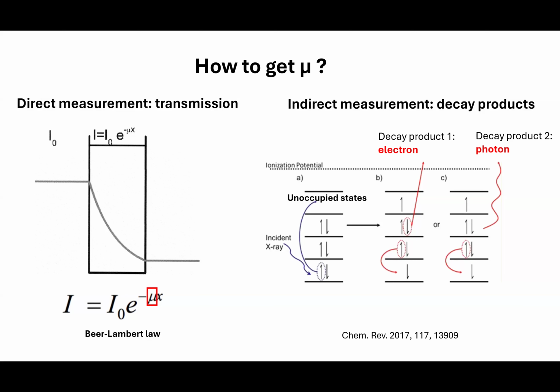which follows an exponential decay relationship between your sample thickness and the signal you get. So you see this exponential decay, and the absorption coefficient, mu, is sitting there in the exponent, and x corresponds to the thickness. We can also get an idea of how important thickness is in affecting our experiments.